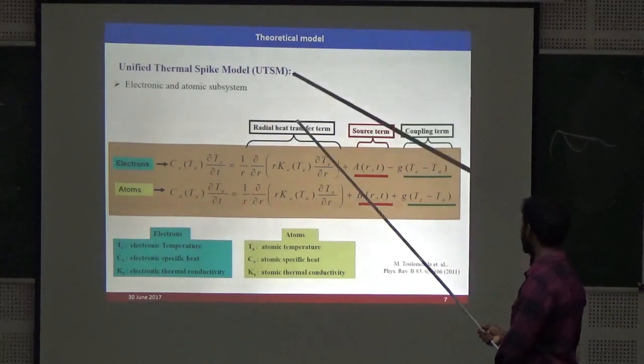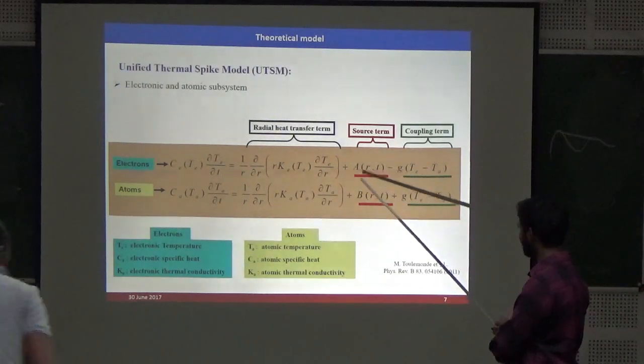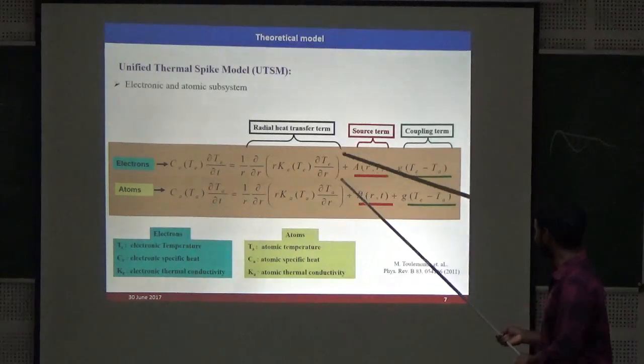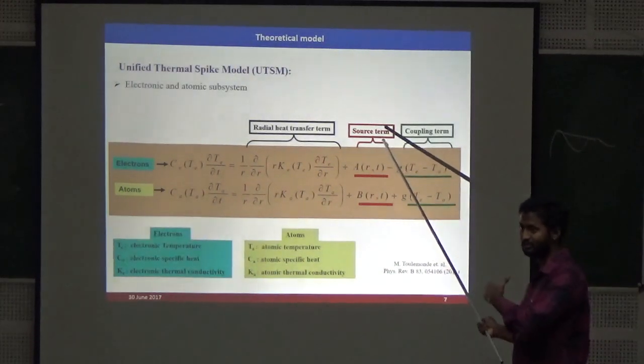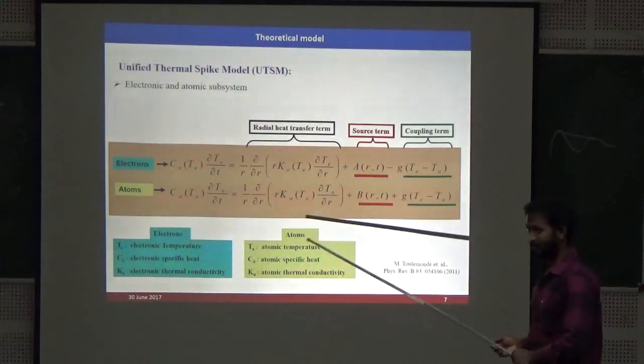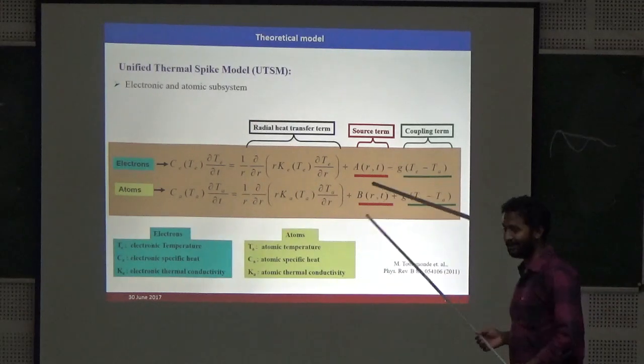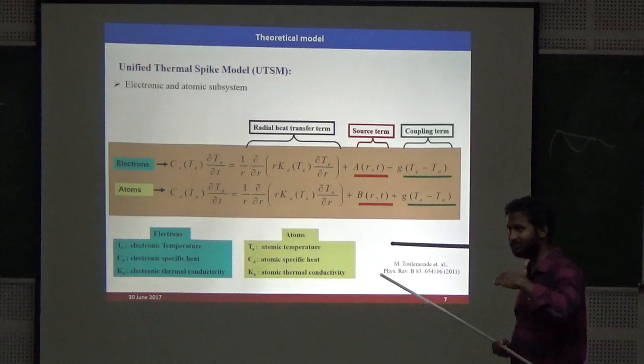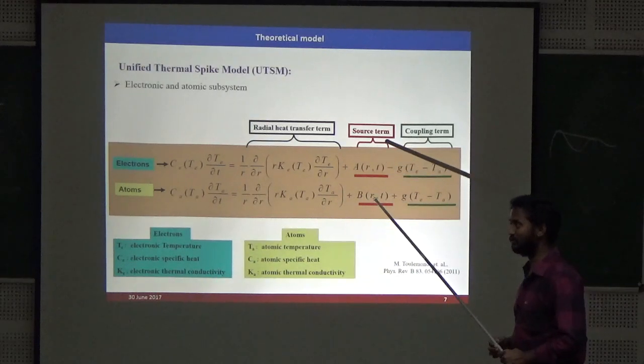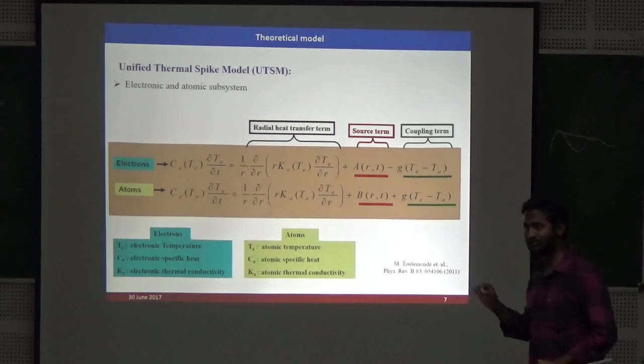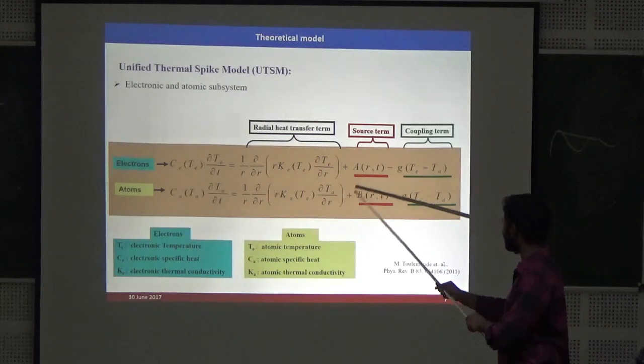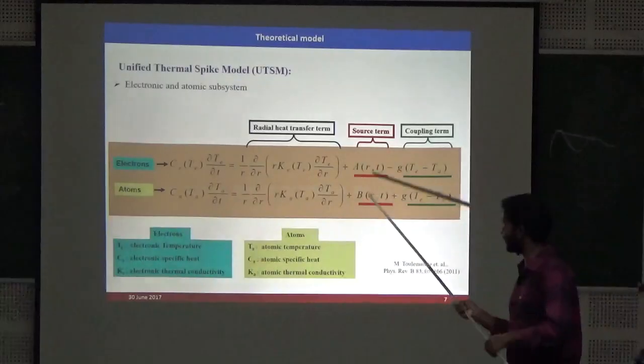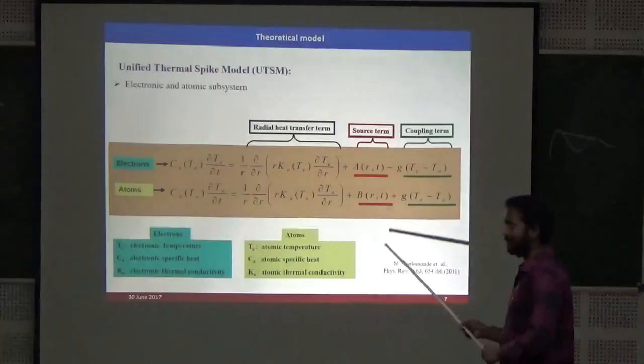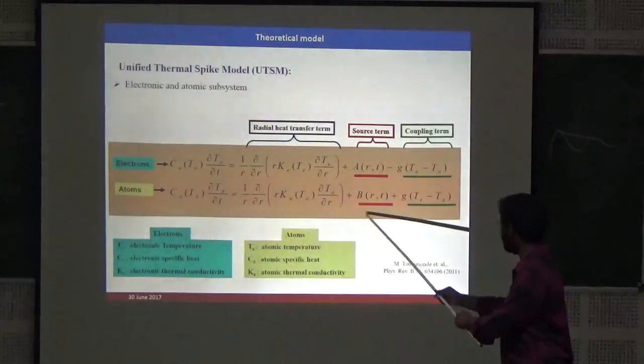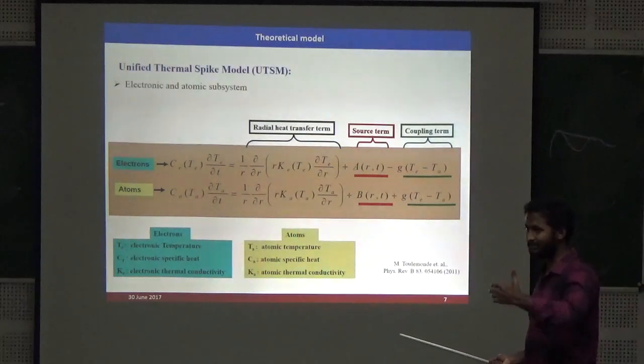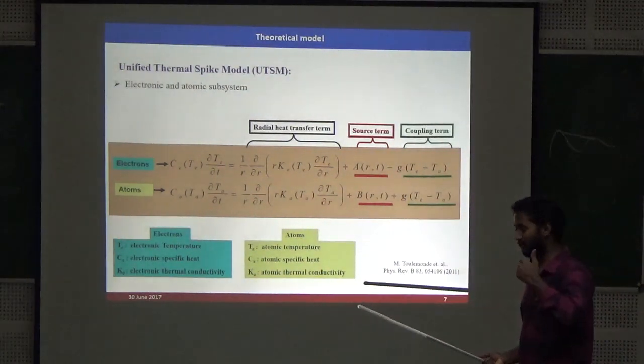In the case of unified thermal spike model, you have a contribution of both electronic energy loss and nuclear energy loss. So how much energy has been deposited? This term is energy deposited into the electronic subsystem, and this one for the atomic subsystem. In the case of high energy ion, Se is too much, which is dominating. In that case, one can neglect the energy given to the atomic subsystem. That is very less, so this term was not there. That was called as inelastic thermal spike. If you include this nuclear energy loss term also, then you have the full energy term. So in the case of high energy ions, we have chosen only inelastic thermal spike because the Sn is almost negligible.